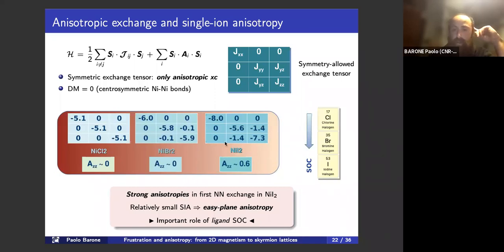So we have a much stronger anisotropic exchange than single ion anisotropy, which in this case would be an easy plane one. So this is a positive term. So there is an important role here of the atomic spin-orbit coupling of the ligand, not of the transition metal. And so, okay, what are the consequences of this anisotropic term?